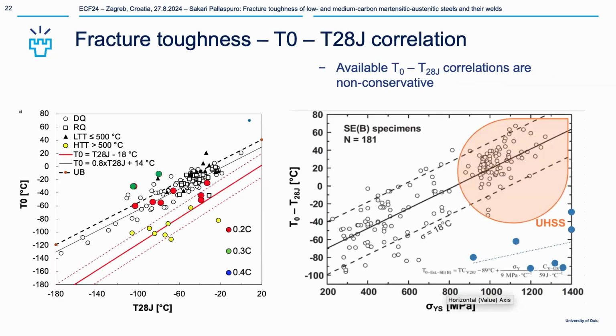But what is the challenge? If you want to employ structural integrity approaches, we see that at least these two widely exploited T28J correlations between the impact toughness and fracture toughness break down when you start to introduce austenite into this matrix. So basically, we are here on the completely non-conservative side. And when we look at the difference between these temperatures, we see that for BCC dominant materials, we have a good temperature correlation with a wide range of yield stresses, but when we put austenite there, it falls apart.